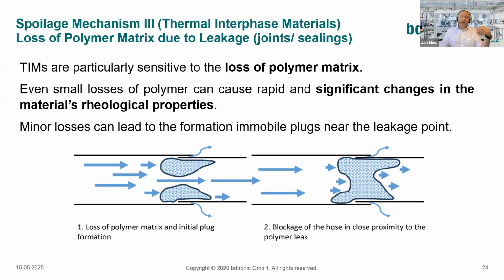What happens next is that the vector of speed in that area slows down, and since more and more polymer is lost, more and more of this solid filler material gets stuck in that area, up to a situation where the hose is completely blocked, which causes, of course, a stop in production and a rework of that position by unscrewing it, removing the material, purging processes, and so on. Could be a downtime of several hours when such things happen. So this has to be avoided.